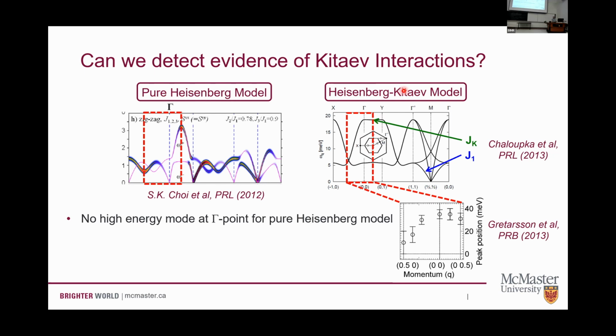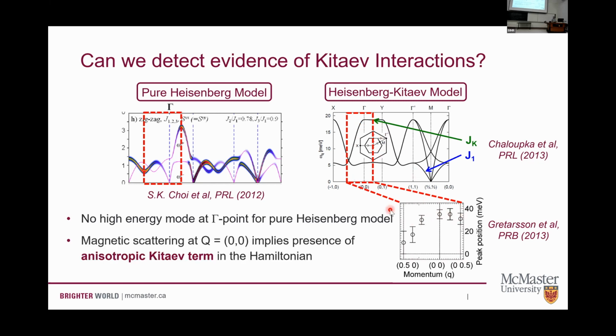And if you compare this to the limited region in reciprocal space that we can map out with RIXS, then this seems to match actually quite nicely to what we've seen here. So the fact that we see this high energy feature, even though it's right on the edge of our resolution limit, this suggests that we might have a Kitaev term here.